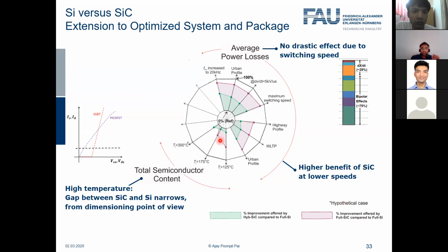So therefore, as we go to higher temperatures, let's say we go to 300 degrees Celsius. This is purely a theoretical point, because silicon cannot really go above 300 degrees Celsius. But anyway, just as a hypothetical case, let's say we can go to 300 degrees Celsius. Then we see that silicon carbide would need more chip area than IGBT, which would not be commercially attractive at all. So the message is that going to high temperature is not really benefiting silicon carbide. And this is quite contradictory to what you might find in literature, because in literature, you see that higher temperature is always good for silicon carbide.